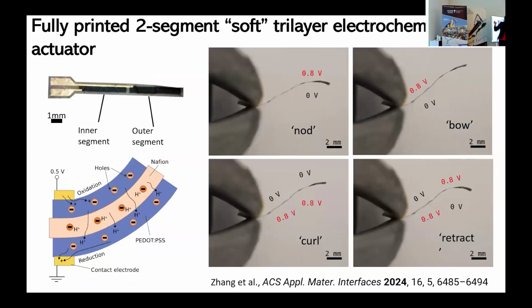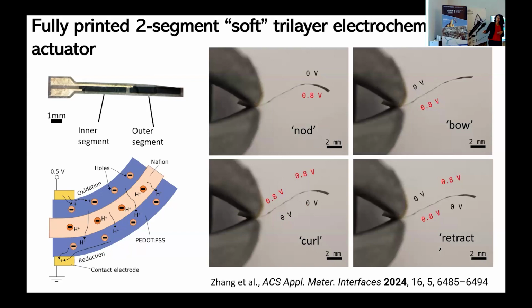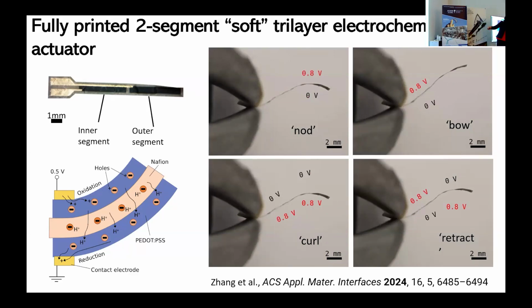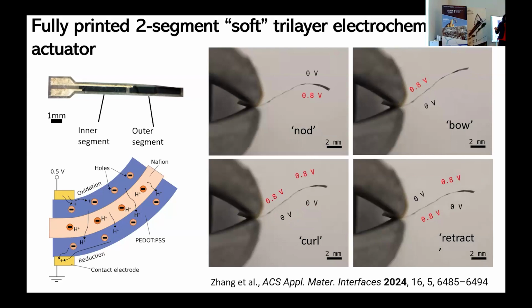And on the other hand, what G has been doing is he's printed this tri-layer electrochemical actuator, which basically consists of PEDOT:PSS on either side, sandwiching Nafion here. And basically, when you apply an electric field, you have oxidation reduction on one end. You have these protons which move across, and that causes this bending. This entire structure is aerosol-jet printed, and so what we reported here is, I believe, the thinnest electrochemical actuator. It's about 10 microns, very, very thin.